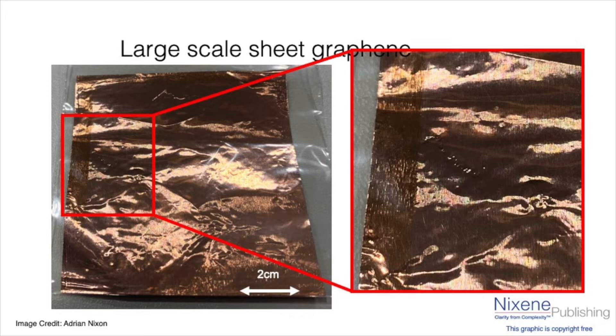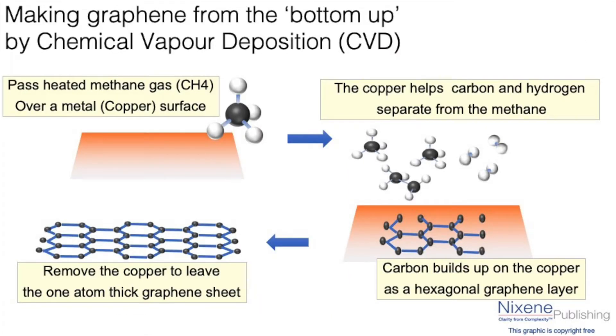Let's unpack some of that for viewers who might not be familiar with the terminology. CVD stands for chemical vapor deposition. Basically, you have a metal surface — copper is used most of the time — and you bring a carbon-containing gas close to the surface and get it very hot, usually methane. The copper acts as a catalyst, allowing the carbon to get close to the surface while the hydrogens from the methane come off as hydrogen gas. The carbon then lands on the surface, coating it in a two-dimensional chicken-wire of graphene. Once the surface is covered, the reaction stops — it's a self-limiting reaction.